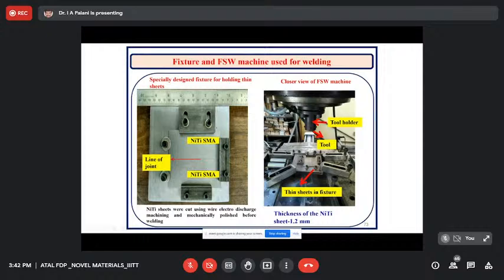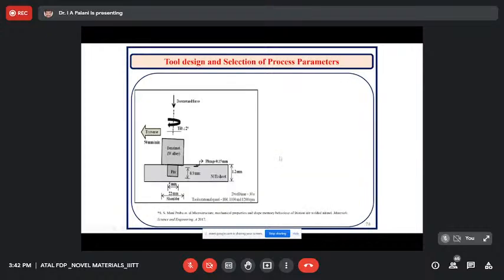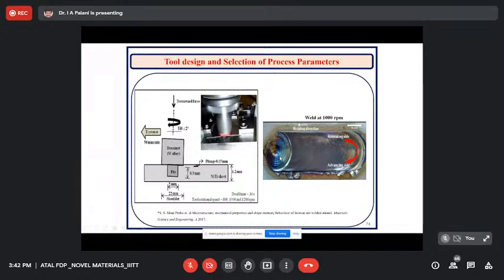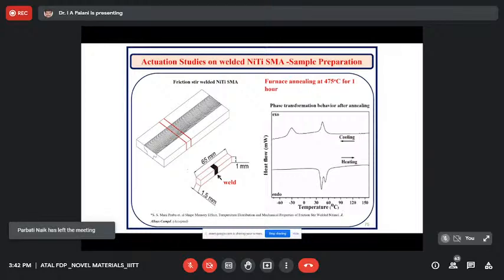This is a closer view of the friction stir welding. In fact, this is the tool design which we have done for it, and this is how our weld zone was looking. You could see that there is no damage or any kind of interface layer observed with respect to nickel titanium. And then we had an arrangement with a pin, and there is a traverse available, and using this traverse we could indent on the surface.